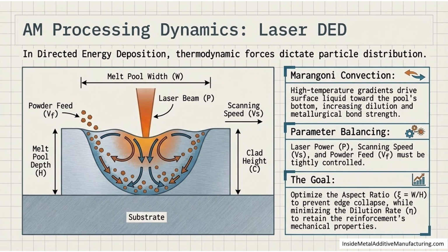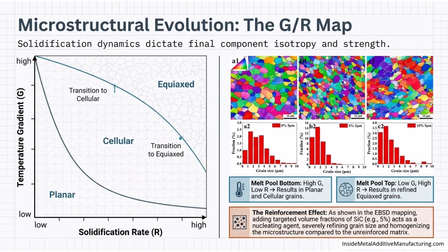High-temperature gradients drive Marangoni convection, circulating liquid toward the pool's bottom and increasing metallurgical bond strength. Our goal here is a delicate balance. We must optimize the aspect ratio to prevent edge collapse while minimizing the dilution rate to retain the reinforcement's mechanical properties. Solidification dynamics, mapped here via the temperature gradient, G, and solidification rate, R, dictate final component isotropy.